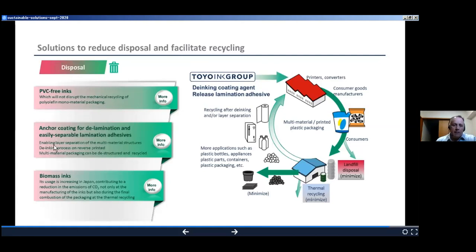Another solution is the anchor coating for delamination, or de-inking anchor coatings, which allow us to remove the ink from the printed plastic, so we can send the plastic free of inks and free of lamination adhesives to the recycling process, so we can get a high degree of purity in the recycling process. And also the biomass inks, the advantage is that they don't generate extra CO2, extra carbon footprint compared to conventional inks. So these are some solutions that Toyo Ink is working on.